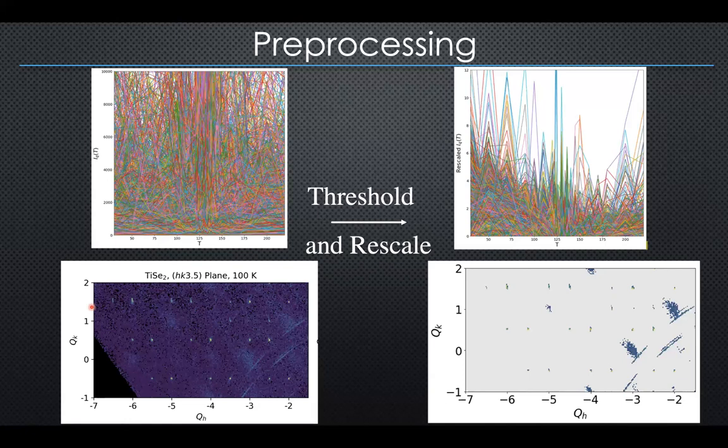Okay. Thank you. Now, the distribution of data is everywhere, but because there is a regularity in the real system, you only hit the atoms at regular angles. As a result, most of the reciprocal space is not really interesting. The action is happening either at the points that are associated with the inverse of the lattice, that's 2 pi over a, or some new periodicity that shows up from this density wave formation.